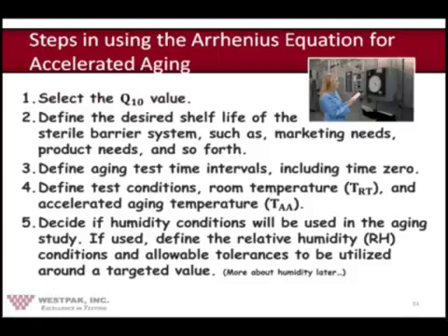Almost everyone that I'm aware of anyway will select a value of 2 initially until you can prove otherwise. And it actually is a pretty good value. Most of our clients use a value of 2 unless they've done specific studies to prove otherwise. And even if they do, it winds up being a very small difference from a Q10 equal to 2.